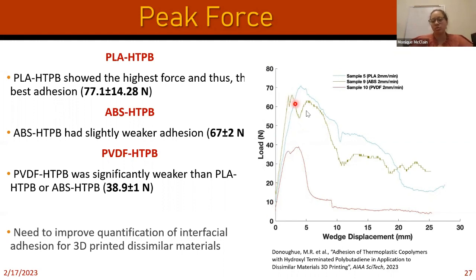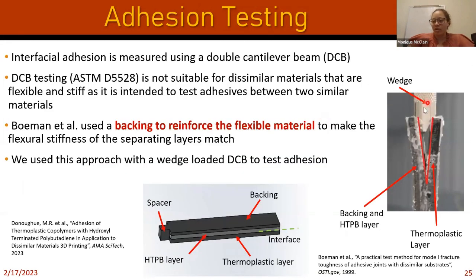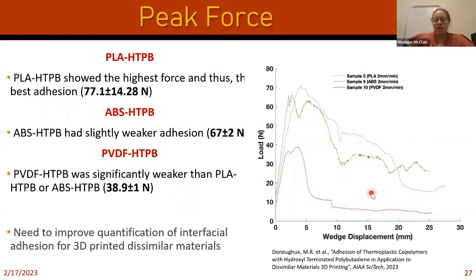We do see some multi-peak behavior, and we want to redesign this wedge interface a bit better, so it's not directly on this HTPB. We're also considering maybe pulling them apart rather than driving a wedge. But in general, we can see some differences in that peak. So either here it's tearing or there are some slight differences. But here the PVDF is definitely, from what we've seen in the sample, peeling. That means it's not that strong of an interface compared to these other materials.